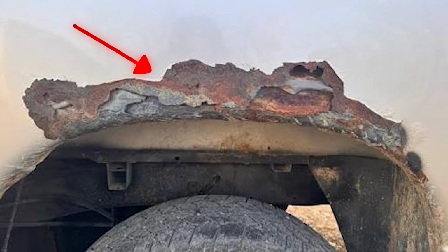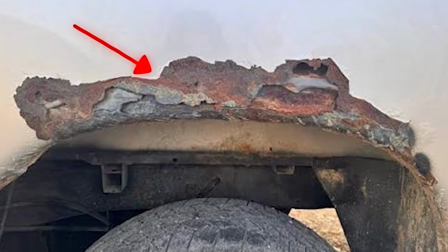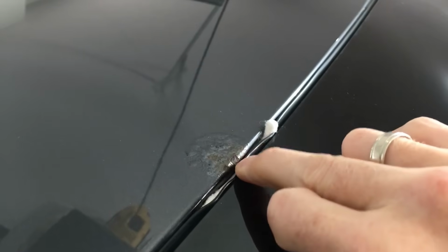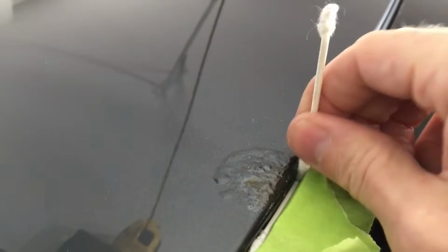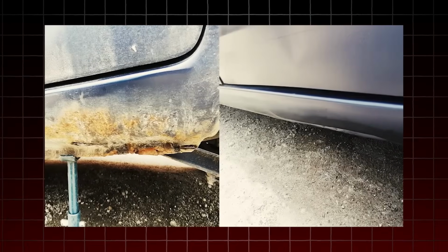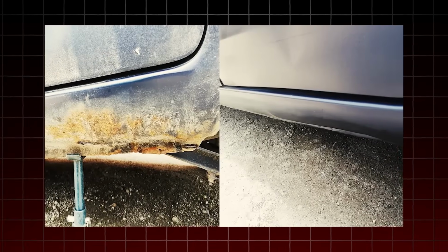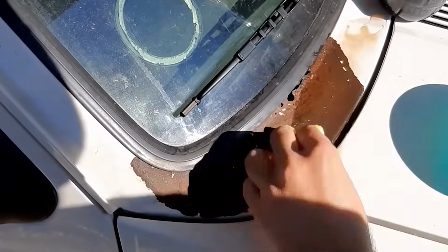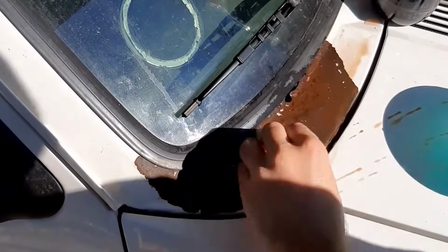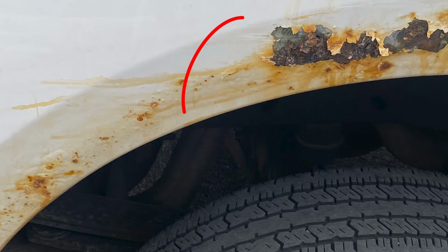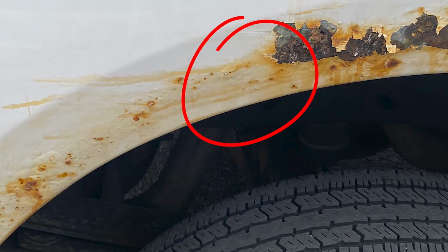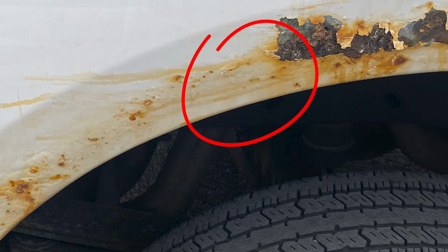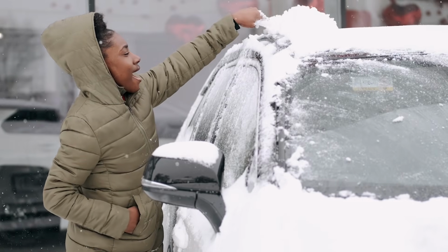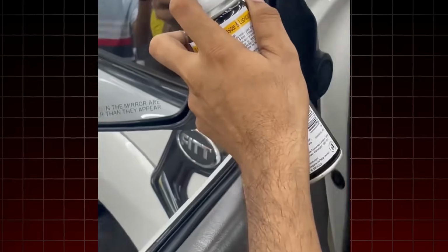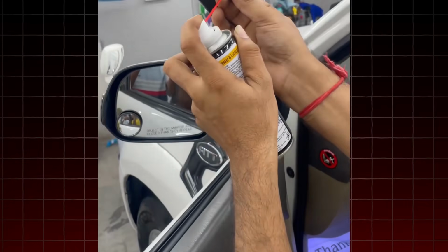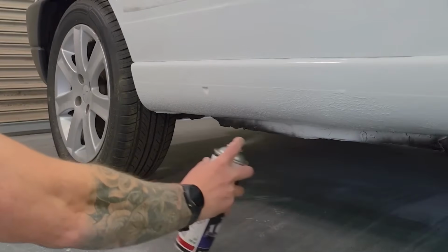The coating does not crack like the Rust-Oleum formula. It delaminates. Entire sections separate cleanly from the metal surface rather than developing micro cracks. Delamination is actually a more severe failure mode than microcracking. A microcracked coating still provides partial protection to the areas between the cracks. A delaminated section provides zero protection to every square centimeter of exposed metal beneath it. By the end of our one-winter investigation period, the 3M formula showed delamination across approximately 22% of the treated surface area.